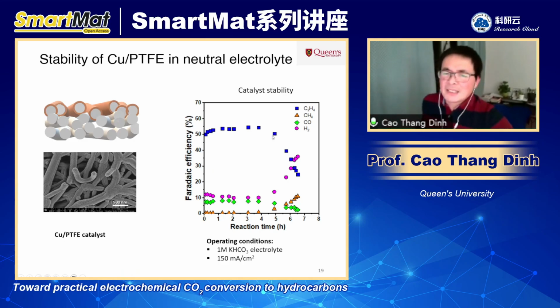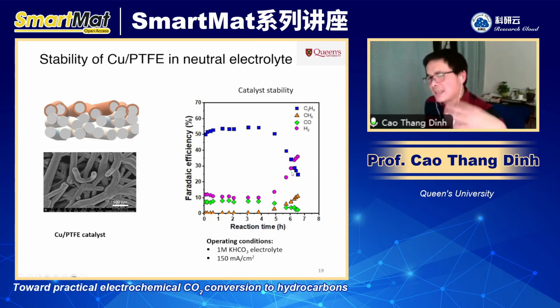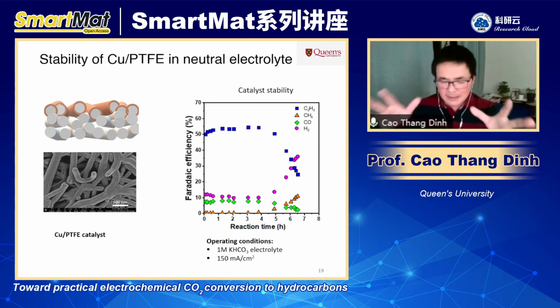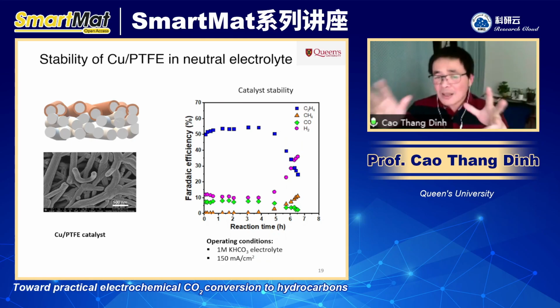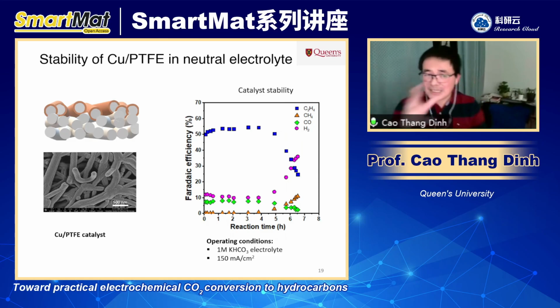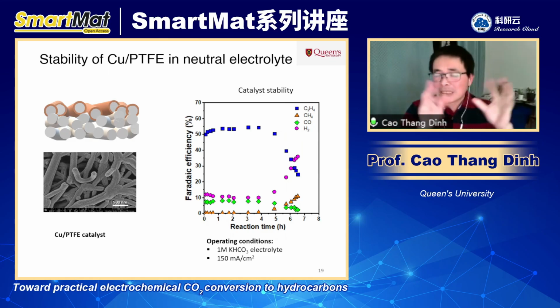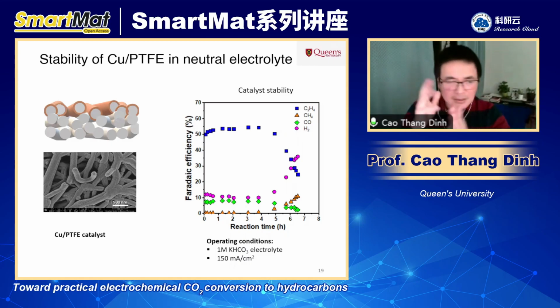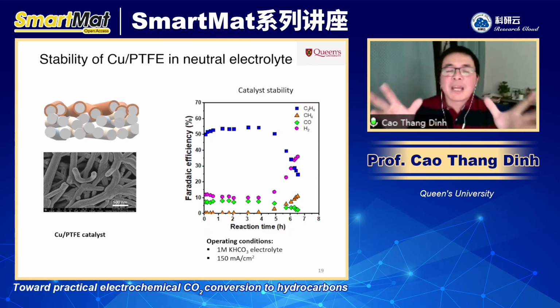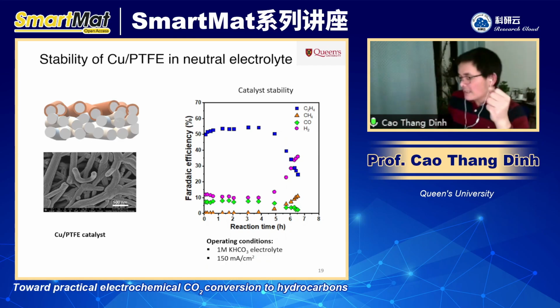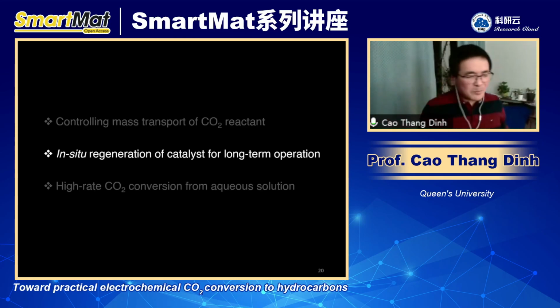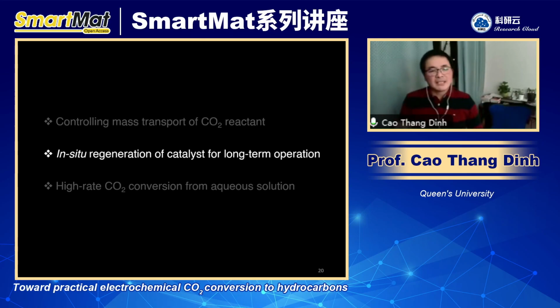As you can see in these figures, after 4 or 5 hours, the ethylene goes down, hydrogen goes up, and methane goes up, meaning that something is going on here. And the problem is not about hydrophobicity or flooding, because we still use the PTFE here, and we did not see water on the backside, and we did not see salt formation in this short time and in this condition. So there must be something happening to the catalyst. Okay, so that leads us to the second part of my talk today: what would be the strategy to overcome the stability problem of the system when something happens to the catalyst?